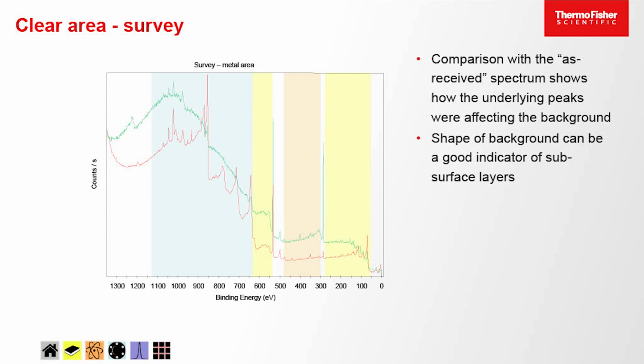So you can see now the backgrounds are starting to curve down, and we can start to see some more peaks. So what was just this shapeless blob here, now we can see these peaks here. We can see this doublet here, some more peaks here, load of other little peaks here. This carbon peak is now much smaller. The oxygen peak's a little bit smaller as well. So what we want to do now is actually start to identify and quantify what's present.